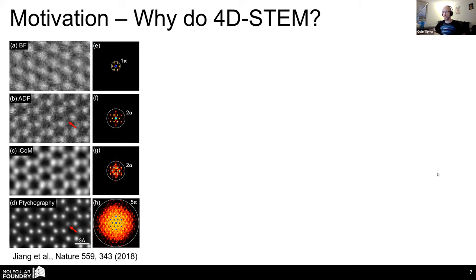And you can see where the red arrows are, where a single sulfur vacancy occurs. It's much, much easier to measure such phenomenon if you have a much clearer, higher SNR image like we see here. So that's on one extreme length scale.